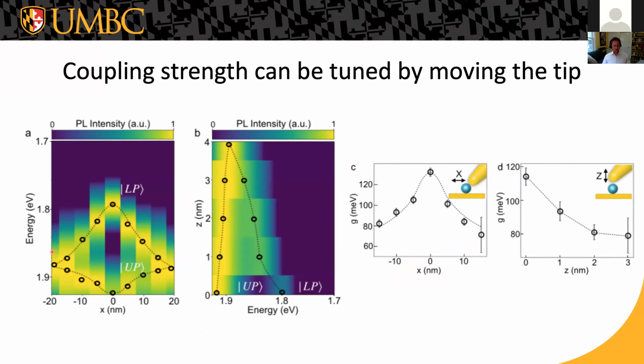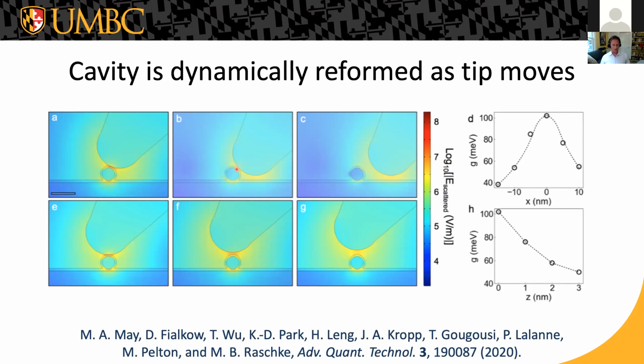If you're scanning laterally, on the other hand, if you move over but are still in contact with the dot, you haven't made your mode a lot larger, you've just changed the mode that you have. You've reconfigured the localized field inside this cavity. The mode volume is slightly larger, but not significantly larger in this case. It's only when the distance from the quantum dot is comparable to the radius of curvature of this tip itself that you start to get back into the weak coupling regime.